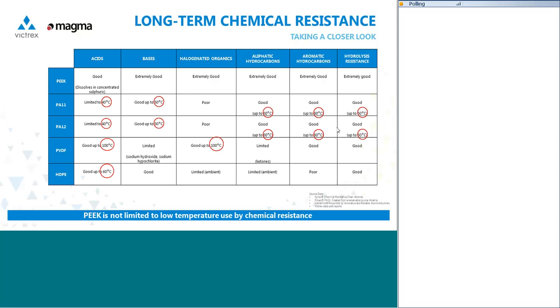That's where you really have to think carefully about the chemicals you're putting down the pipe. Even with PVDF, which has improved thermal and chemical properties, by the time you get up to around 100 degrees centigrade, that's probably about where the chemical resistance begins to bottom out for that material. And remember that that material in particular will melt at around 165. So as soon as you're getting up towards that melting point, you would expect your chemical resistance to be dropping off.